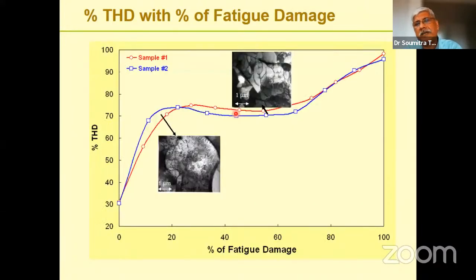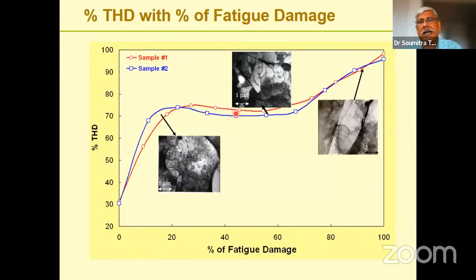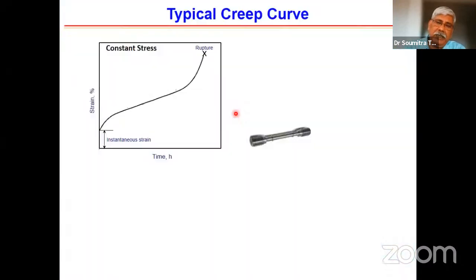We also studied at various levels the dislocation configuration, to understand the type of dislocation configuration that takes place with fatigue damage and how it progresses to ultimately initiate a crack. So that was one of the studies. Similarly, for creep, we tried to understand if creep damage can be quantified using non-destructive, nonlinear ultrasonic.